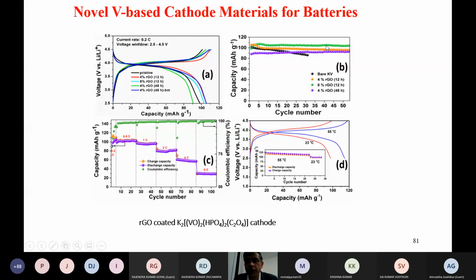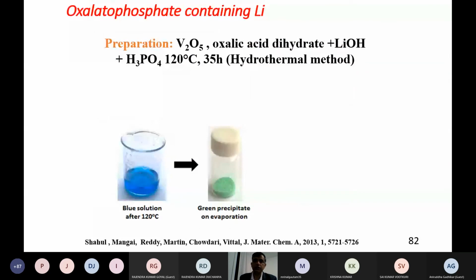As you can see, at the end you may ask, engineers may say, why don't you use this material for applications? I can tell you no. Why? The reason is that the benchmark material is around 150 or 130 milliamps, although we claim it as a new material. So we are still a little bit less than the benchmark material. Sometimes, although we claim a very fantastic material, in reality, if you go to real industry, they look for high capacity, high performance is needed for real applications. Again, we can do lithium-containing and other types.